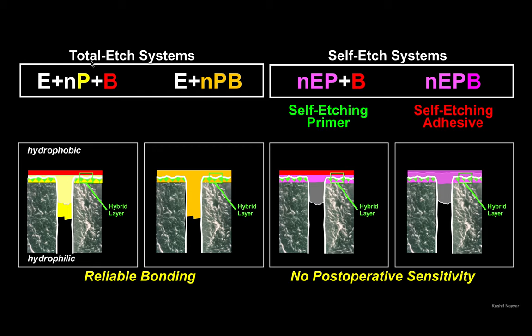So let's understand the classification on the basis of smear layer and smear plug removal. On the left side you have a total etch system in which you have to use a separate etchant. Whenever you are using a separate etchant, you are completely removing the smear plug. No doubt it is giving you a reliable bonding. On the other hand, you have a self-etch system in which the primer itself is acidic in nature, so you don't need any separate etchant. So the steps are minimized in the seventh generation, in which only one bottle was capable of etching, priming, and bonding. And what we are looking at here is that the amount of smear plug being removed is not complete, and it is giving us no post-operative sensitivity whenever we are using this type of system.